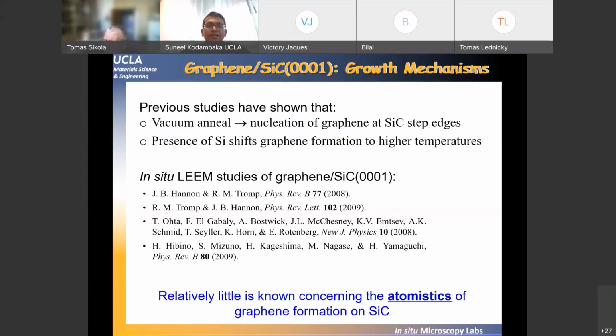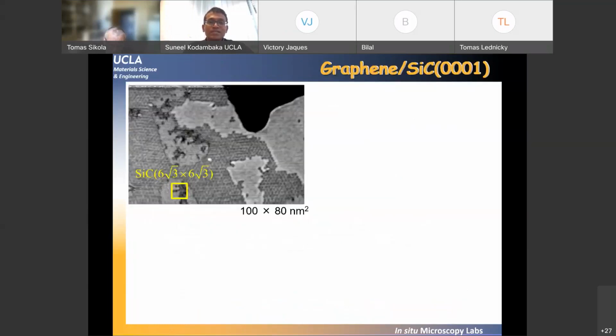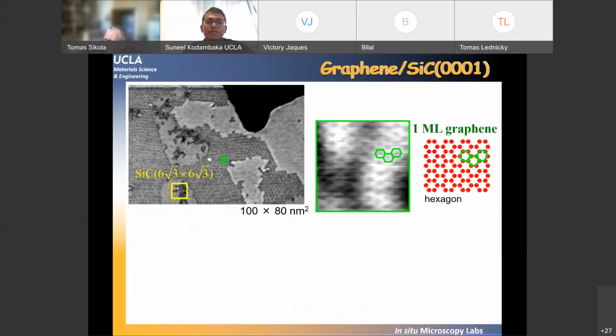There are a lot of studies that have focused on controlling the growth orientation and the quality of graphene on silicon carbide. There are a lot more references than I can cite here, but I've chosen a few that I thought at that time were focused on the growth-related aspects of graphene on silicon carbide. And all these references point to the use of LEEM to study the growth of graphene. What we did is complementary to this, to use STM to study this. And one of the interesting and fortuitous aspects that came to our rescue was the surface roughness of the silicon carbide.